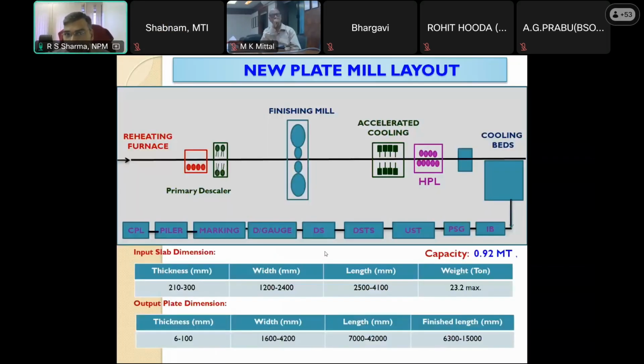This is the new plate mill layout. As you can see, there is a furnace, then after that there is a primary descaler. After heating in the furnace, the slabs are descaled in the primary descaler at 220 bar, very high water pressure, so that all the scales generated on the slab during residence in the reheating furnace for more than 3 hours are removed. Because if they are left as such and rolling is continued, these scales will be rolled into the parent body, and that will result in rolled-in scale.